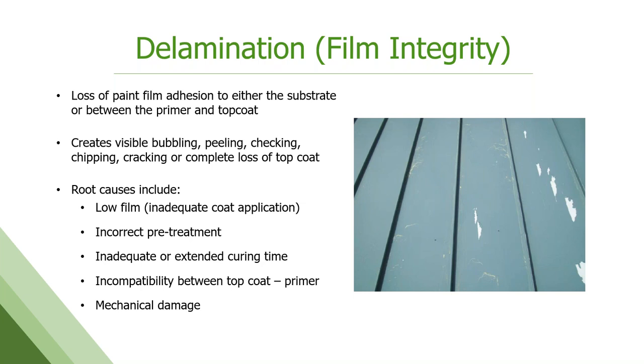It could simply be damage at the time of installation or damage that has occurred while the roof was in service, either during cleaning or from the glacial effect, places where there's snow load that doesn't have snow stops and that snow slides down these panels and leaves scratches that then open up over time and you get loss of paint. So it's a very difficult one after the fact to know exactly what happened.